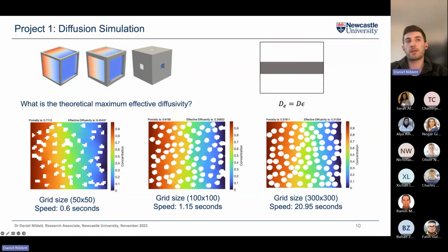And so I tested the model to see the speed of the model at different resolutions. So as I increase the resolution, you go from half a second for a 50 by 50 grid size, but you don't resolve the structure that well, to 20 seconds per simulation for a 300 by 300 grid size. And now it's important to have this fast simulation because I can just give it an image now and it will be able to predict and characterize in seconds what is the performance of that structure, which we can move through to the genetic algorithm in the next phase.